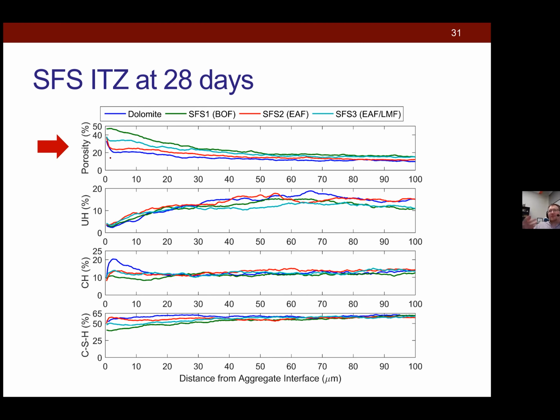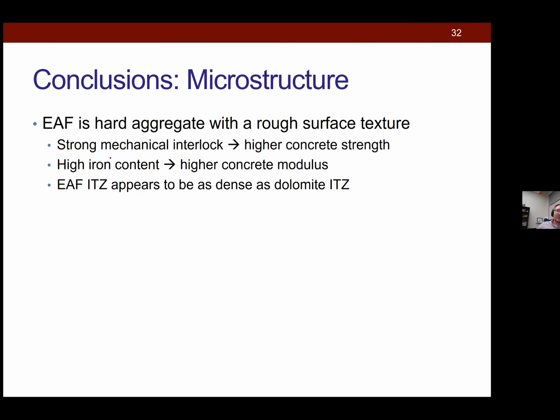So that steel slag number 2, we found the ITZ actually behaved fairly similarly to our control, the dolomite, right? And that's the one that gave us the highest strength increase. Whereas the BOF and the LMF, so slags 1 and 3, both had some reductions in strength relative to that. And we did find that there was a higher porosity there too, right? So that's another way we can now relate why we've been seeing those reductions in strength.